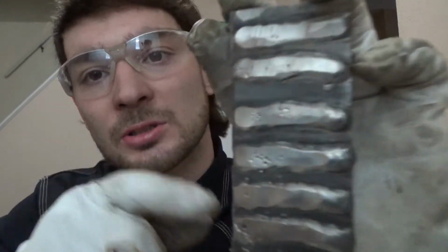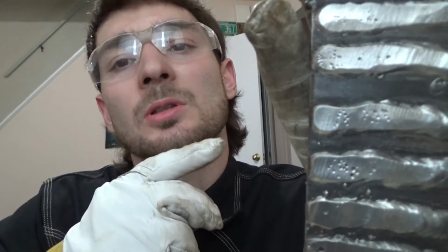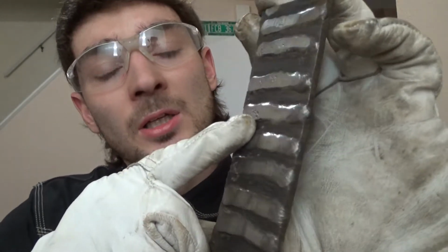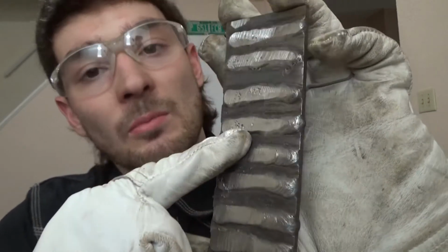And all four of these are 7018 beads, where I somewhat induced the porosity on that original bead and ran over it. Although it didn't crop up to the surface of the second weld, you could see it's still in there, and it certainly does not burn that porosity out. So that just goes to show you that porosity is certainly a discontinuity that you want to address if you're taking a test, because on an x-ray it would see all that. It would see these clusters of porosity, and a couple of these, that one in particular, would perhaps be cause for failure. I forget exactly what the criteria is.